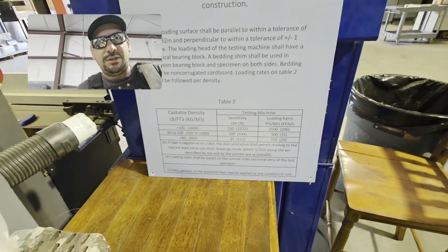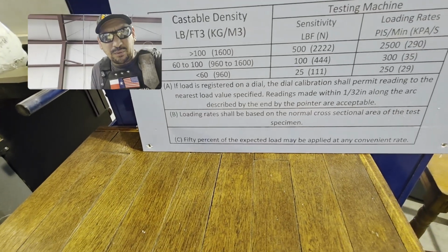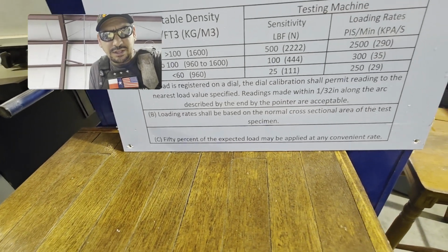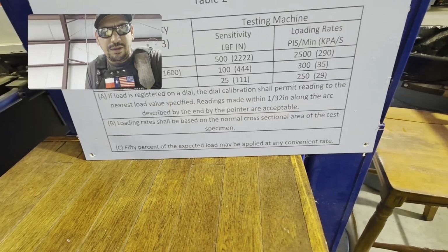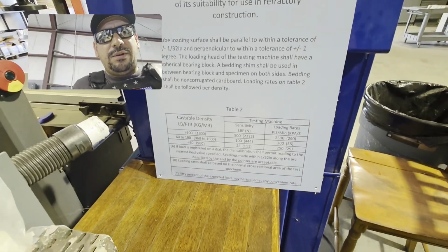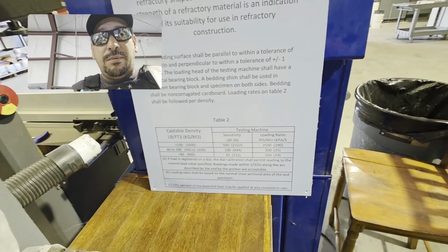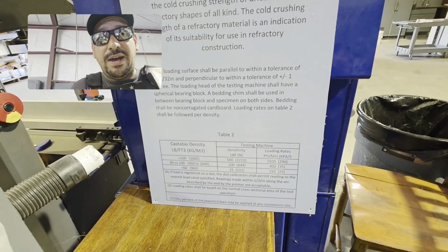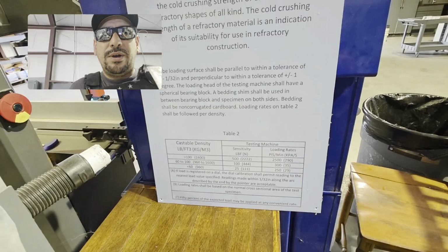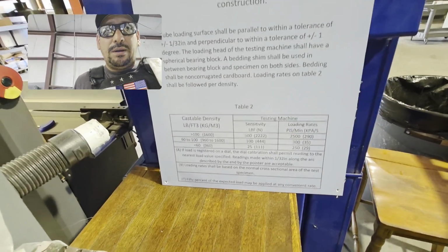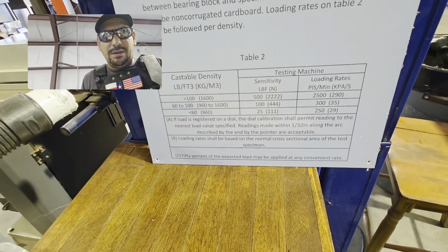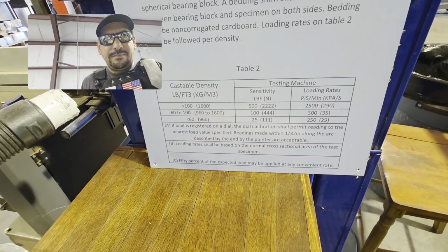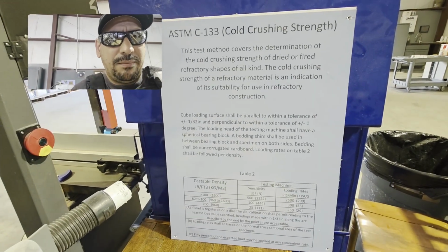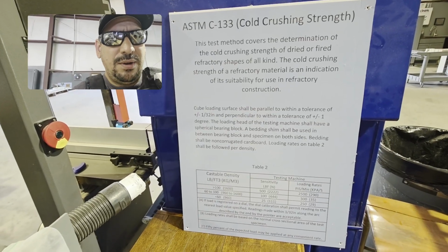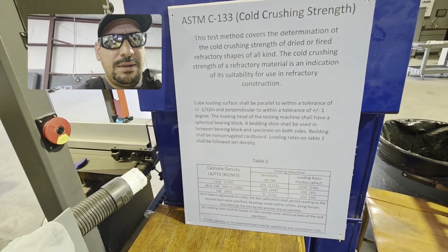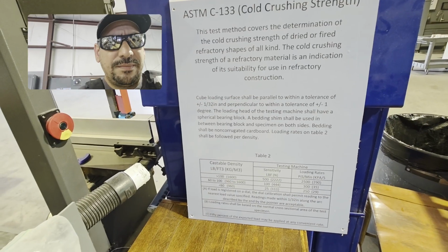Now, here's a little trick. The very last portion of this says 50% of the anticipated load may be applied at any convenient rate. So, for instance, if your material is going to end up crushing at a total of 5,000 psi, you can run it up to 2,500 psi at any rate you want. After that, you're supposed to be following this chart. So you might want to stop now and take a screenshot of this so you can remember, because these are very tricky questions.